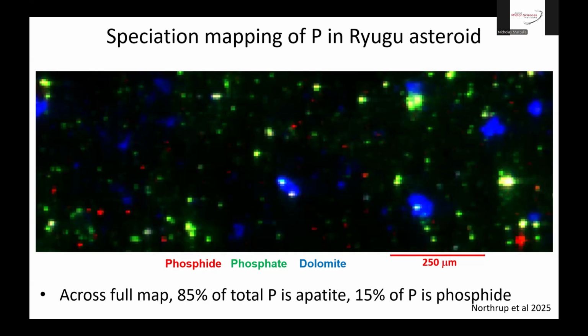By integration, do you mean expanding the number of the grid itself? Yes. Basically, if you analyze the whole map, the integrated intensity of the phosphide signal, or the red, and the integrated intensity of green over the entire map. Since they were generated by the intensities of those, measured at those two energies, that actually does relate to concentration. There's a bit of a matrix effect that comes into play, but approximately it's that ratio.